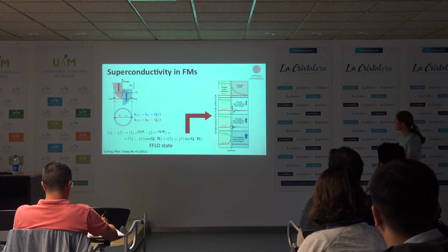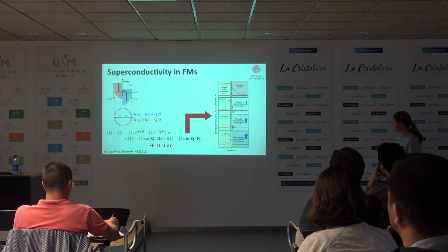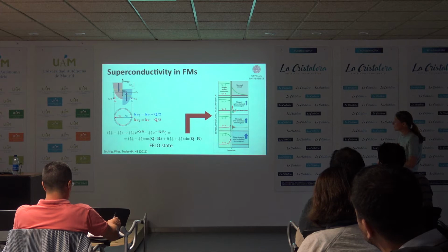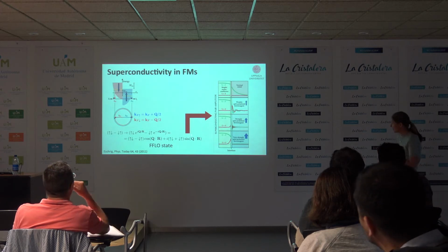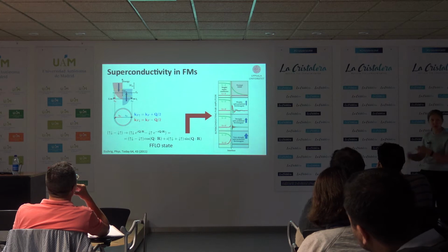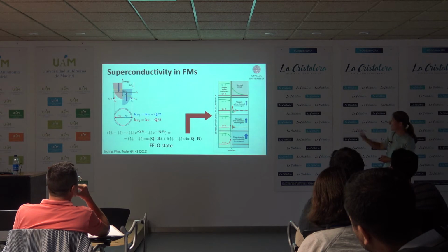So what happens at this interface? This schematic is trying to explain it. If you start with a spin singlet superconductor and you have a normal metal, the spin singlet can leak into the normal metal like this. There's no spin triplet. If you have something that's weakly polarized, the spin singlet goes into the mixed spin triplet, and then it starts oscillating. This is these cosine and sine factors here. If you have something that's strongly spin polarized, it starts oscillating faster, right? The big Q is bigger, and you also lose some pairing on the superconducting side. This is an inverse proximity effect, where you lose Cooper pairs, because a ferromagnet also influences the superconductor.